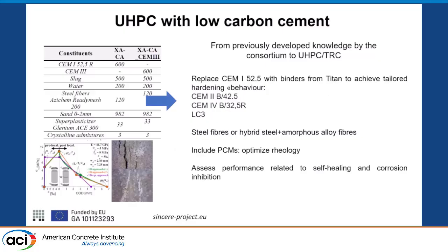So we started, this was the material that we used in the original project, and as you can see, you have CEM I, 600 kilos per cubic meter. We have a lot of slag. The replacement ratio, or basically the volume ratio between cement and slag is 50 by 50 in the total binder content. And we had about 120 kilos of steel fibers, which is about 1.5% by volume.